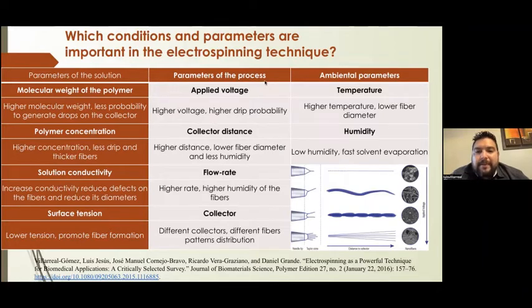In the case of the parameters of the electrospinning process, you need to vary the applied voltage, the collector distance, the flow rate, and the type of collector. Depending on the collector, you will have a different distribution of the fibers, and depending on these parameters, you can have thinner or thicker fibers, depending on the application that you want. We also have to take into account environmental parameters such as temperature and humidity. If you don't control these parameters well, you will have thicker fibers, or you will not be able to create fibers.